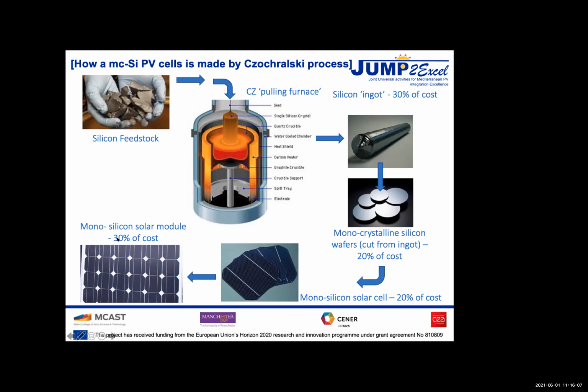The cost of the actual cell is quite low. So what happens, relevant for the rest of my talk, what happens here? Oxygen gets incorporated because we have a silica crucible, silicon dioxide crucible. That has historically been viewed as a good thing, because oxygen performs the role that carbon does in steel. Oxygen hardens the silicon so it can be sawn into thin wafers. So that's good, but then we shall see later on that oxygen is bad in some ways.